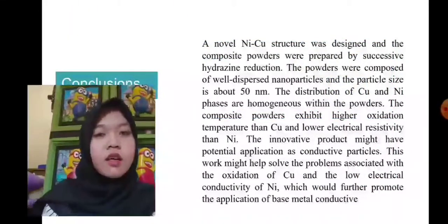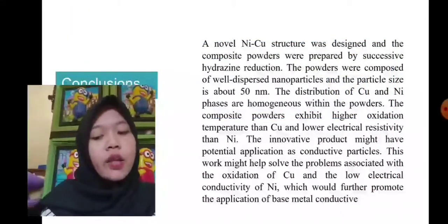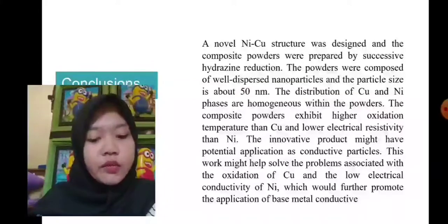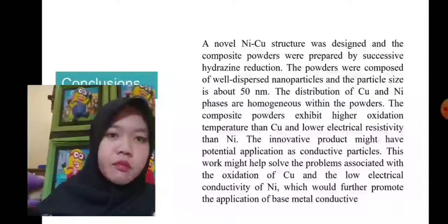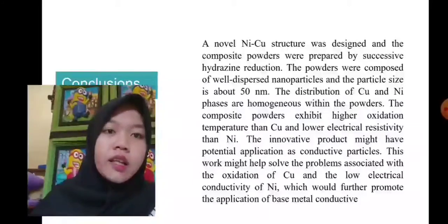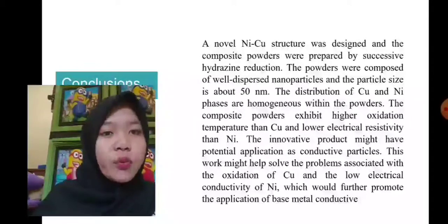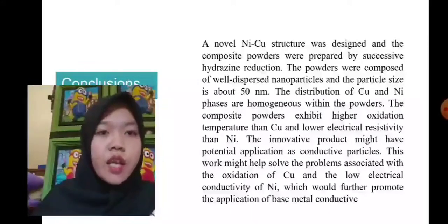Okay, let's go to the conclusion from this article. A novel nickel copper structure was designed and the composite powder was prepared by successive hydrazine reduction. The powder was composed of well dispersed nanoparticles and the particle size is about 50 nanometers.